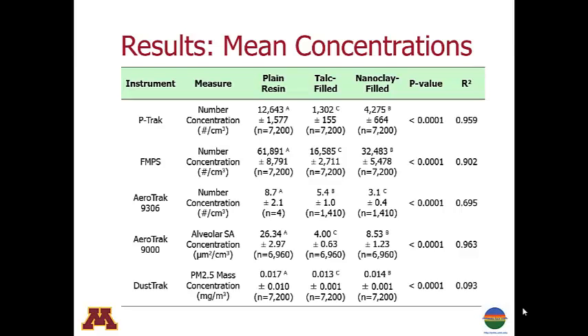This table shows the mean concentrations measured for each type of resin with the four instruments we've already looked at, as well as for the AeroTrack 9306 optical particle counter, which looked at number concentrations for larger particles. You can see for the P-track and the FMPS the same results that we saw in the figures, where the plain resin produced higher concentrations than the nanocomposite material, and the nanocomposite material had higher particle concentrations than the talc-filled resin. The same pattern is observed for the surface area concentrations. For particles 300 nanometers in diameter and larger, the AeroTrack 9306 data show that number concentrations were very low. This is consistent with the dust track observations where we saw that mass concentrations during shredding were close to the background levels when the granulator was turned off.